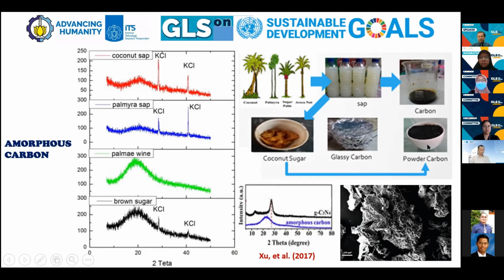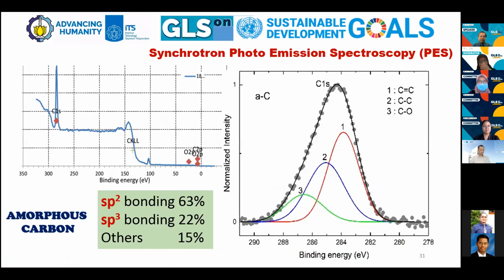Okay, so this is the carbon powder from the coconut sugar, and also from the sap, and also from the sugar itself. And you may convert this powder into a liquid by adding some solvent to make a solution, and also coat it on a substrate to become a thin film. Furthermore, the amorphous carbon sample from brown sugar contains around 63% of sp2, meaning the graphitic or graphenic phase, and 22% of sp3, the diamond-like carbon structure, and the rest is other. It means the amorphous sample is dominated by graphene bond, like this one, sp2 bonding.